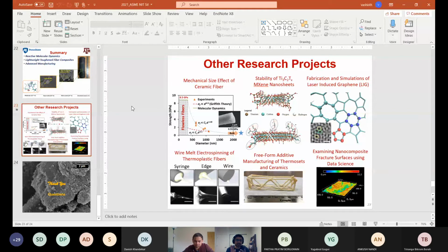The nice thing about MXenes is that apart from this titanium, carbon, titanium layer, you have surface functionality also. There are some surface groups, which could be fluorine, OH, oxygen, and if you think about it, there are so many small knobs that you can turn to change the properties. In graphene, you basically have a layer of graphene. If you add oxygen or OH to it, the best you can do is make graphene oxide or something.